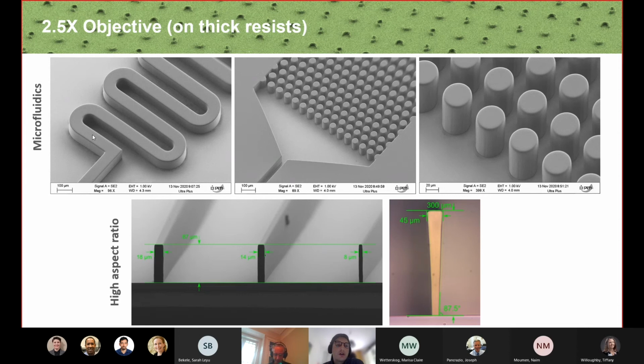You have some examples here of a microfluidic channel made in SU8, and 2 examples here of a cell sorting device. You can see that the walls are very steep and of very good quality. By using this high depth of field objective, we can also reach very high aspect ratio structures. On the bottom side, you can see that on this 90 micron thick resist, we can reach 8 micron structures, which gives you a 1 to 11 aspect ratio. And we can also do very thin structures here, a 45 micron pillar on a 300 micron layer. This can be really useful when you have to work with high aspect ratio structures.